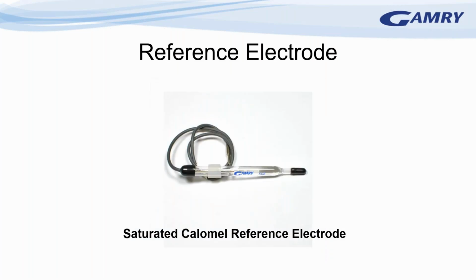The reference electrode is used because the potentials that we measure are on a relative scale, so the reference electrode has to have a stable, constant electrochemical potential, and so it uses an electrochemical couple that has a stable potential. Common aqueous reference electrodes are like the one shown, the saturated calomel reference electrode, but could also be something like a silver-silver chloride reference electrode.